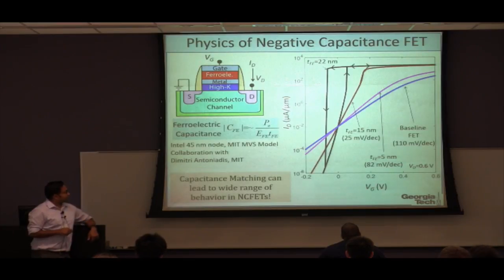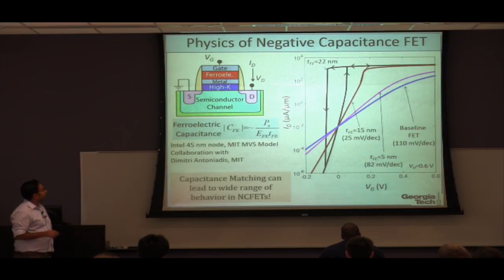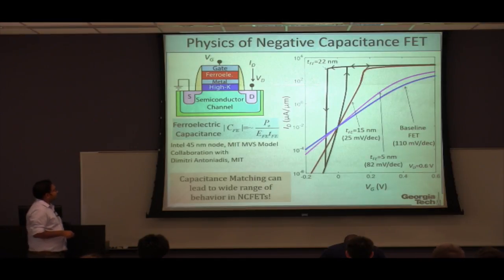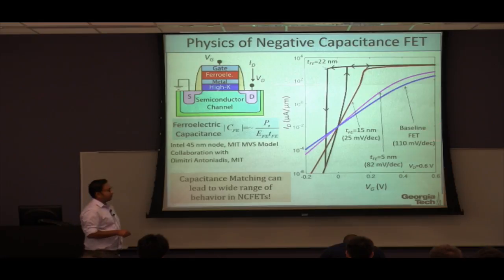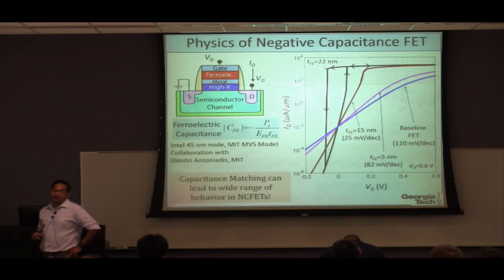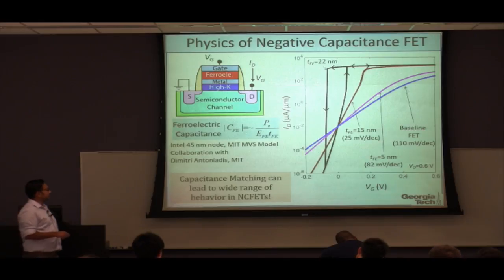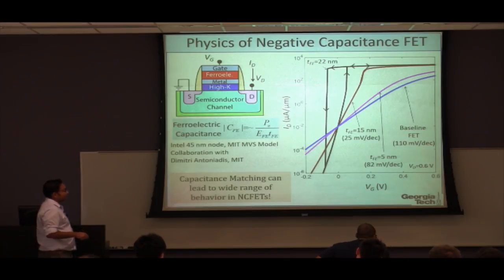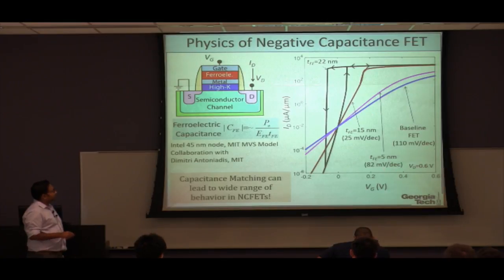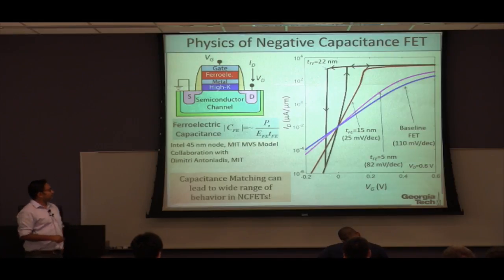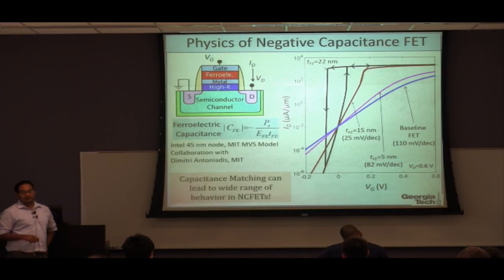So these are some simulation results of a transistor. This blue curve over here is the current voltage characteristics of a transistor that does not have a ferroelectric gate oxide. And it has a subthreshold swing of 110 millivolts per decade, much larger than the limit. Now, if we include a 5-nanometer thick ferroelectric film here, then we can clearly see that the curve has become sharper, and the subthreshold swing has gone down to 82 millivolts per decade.